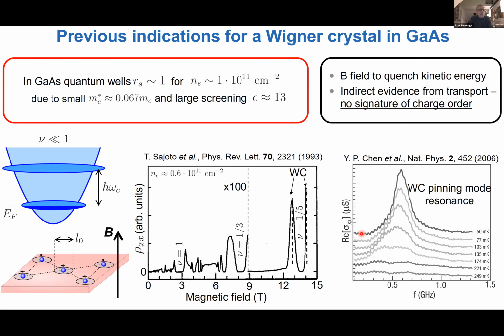So naturally, this is a very interesting prediction by Wigner that has fascinated physicists, and there have been intense efforts to observe Wigner crystals over the last 30 years. The material of choice in this regard is gallium arsenide, and the principal reason is not its high rs values. On the contrary, rs is small in gallium arsenide. It's about 1 for electron densities of 10 to the 11, but the quality is very high. This is the highest mobility system that we have at the moment, where the mobility can exceed 30 million.